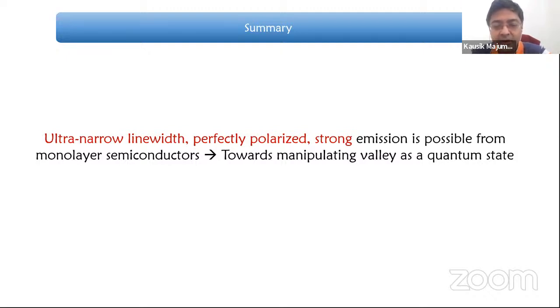Right. So for the first part, I guess you are talking about trapped states, right? So yeah, one of the advantages of trapped states is that the scattering mechanism is slightly different. And I believe that because it's quantum confined, the scattering is going to be suppressed, right? So there's a second part of that also, that how much valley nature these trapped states are going to retain. Meaning that these trapped states don't have to come from the K or K prime valleys, right? It can be anywhere in the entire Brillouin zone, right?